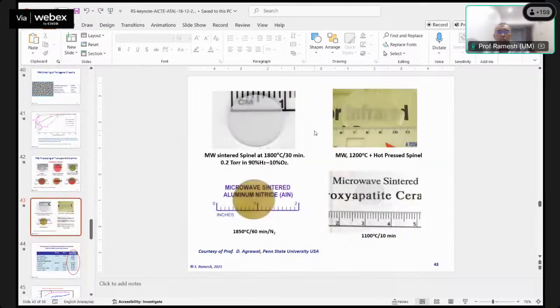All right, so these are spinel. These are hot press spinel. These are aluminum nitride. And this is hydroxyapatite. This is my HA. This is the HA that I've developed in my lab, subjected to microwave at 1100 for 10 minutes. And you can see this is the sample. It is transparent and it is fully dense.